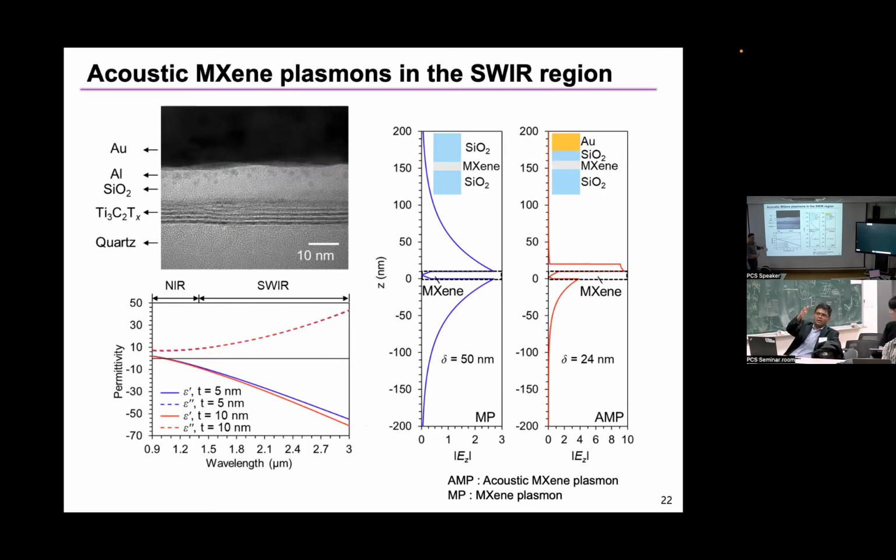But your TEM shows that cannot be assumed to be true. Yeah, effective value, right. Which are clearly insulating in between. Yeah, good point. So electrical conductivity is in the in-plane direction. In the out-of-plane direction, electrical conductivity is very low. Thermal conductivity is also very low.